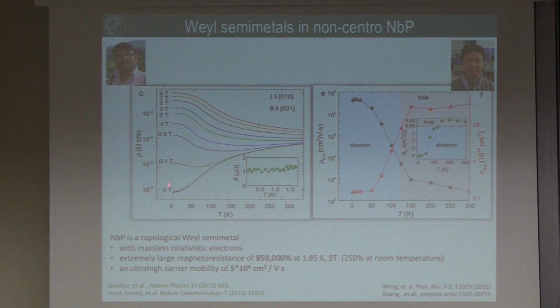And then if you apply a very small field, it already changes drastically the resistance, and then at higher field it looks more like a semiconductor, which goes flat into zero at zero Kelvin temperature, which is a unique feature of all these semi-metals.